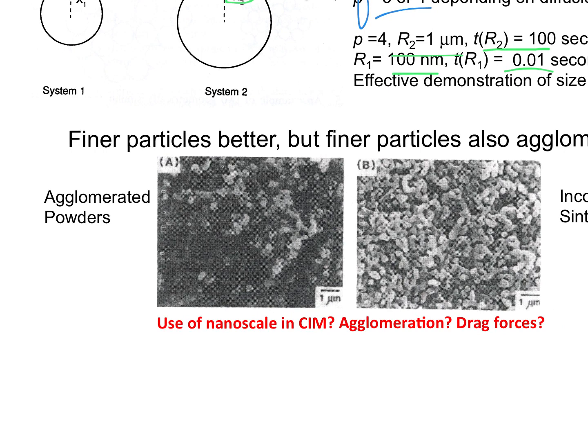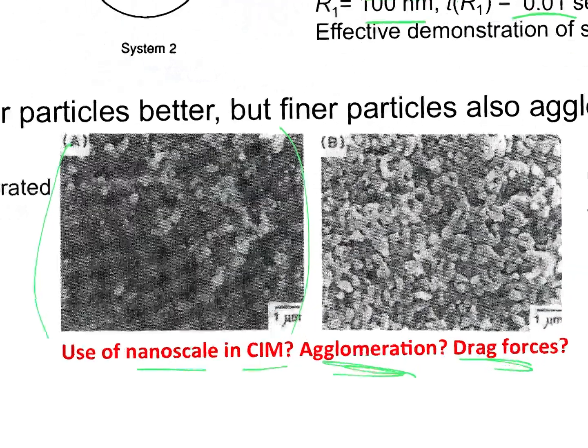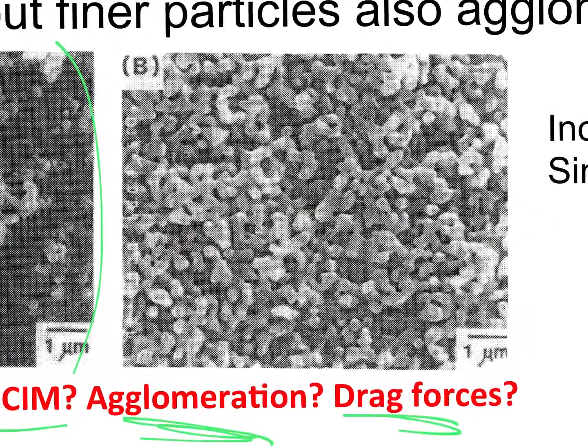And so you see the impacts of this in the use of the nanoscale in ceramic injection molding, and you worry about things like agglomeration and what kind of drag forces are necessary to get to these types of microstructures, which are pretty good. So we have this 1/7 rule, different particle sizes. We've formed the compact. We remove the binder. You know about that now, and we start to sinter it. You form the necks, and it starts to look like a sponge at this point.